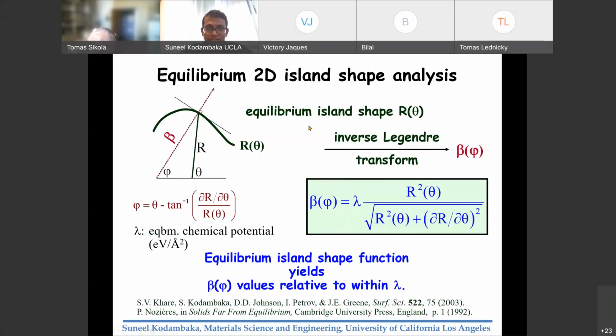And I'll quickly go through this, but if you're interested, I'll be happy to talk to you on this topic. So basically, the equilibrium island shape as a function of orientation can be related to the step energies as a function of step orientation by inverse Legendre transform. And this was done by Nozières a long time ago.